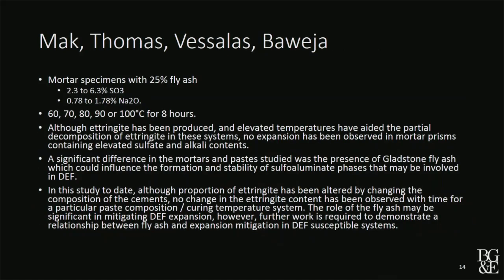So there's been additional work done. This is also work from the UTS, where they looked at mortar expansions. And they were unable to really come up with expansions using the Australian concretes. So again, the studies keep going on. Australian concretes with its low sulfate, low alkali, is more immune to delayed ettringite formation.